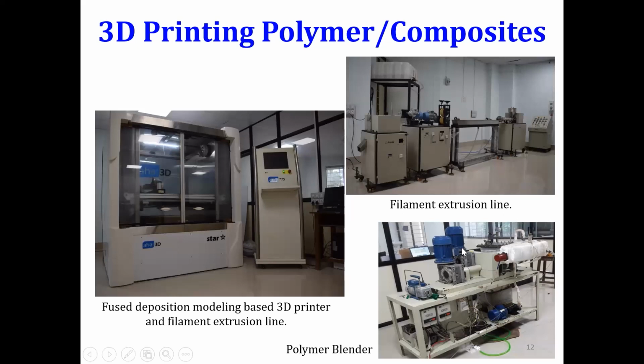This is a polymer blender wherein we blended the reinforcement and the matrix. This is a very crude level of polymer blender, which cost 2 lakhs. But better than this is a twin screw extruder, which will cost you around 25 plus lakhs. In these twin screw extruders there are two screws in a barrel, and because there are two screws in a barrel, you will have a uniform and homogeneous distribution of the filler in the matrix. And whatever outcome comes out of this polymer blender or twin screw extruder, we cut it and put it in a single screw extruder to make the filament.